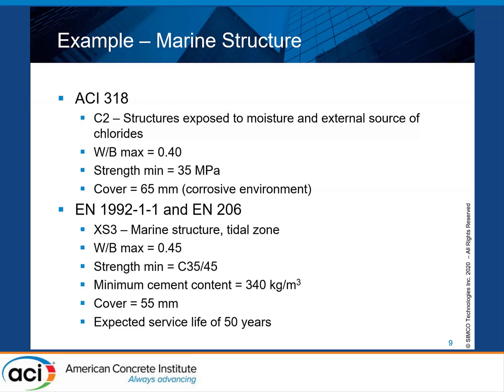I'm going to show you an example here. So I decided to use a marine structure, and following ACI 318, this would be a C2 concrete that is required. It's exposed to moisture and an external source of chlorides. The maximum water binder ratio is 0.4, minimum strength 35 MPa. I converted in MPa. The cover is 65 millimeters for a corrosive environment. So there's a special provision for a corrosive environment. And